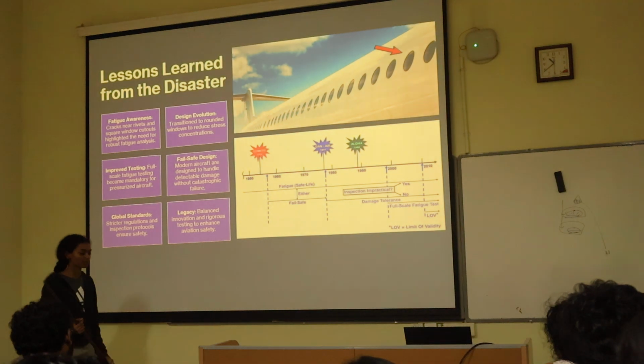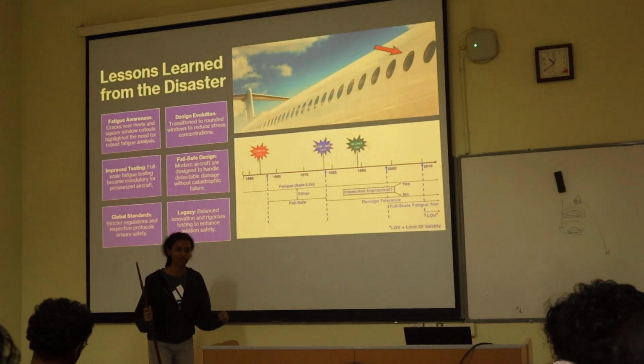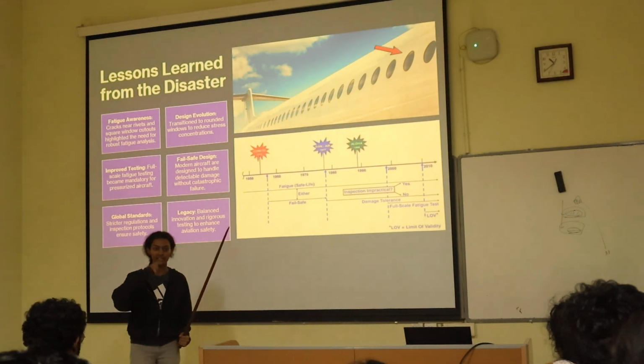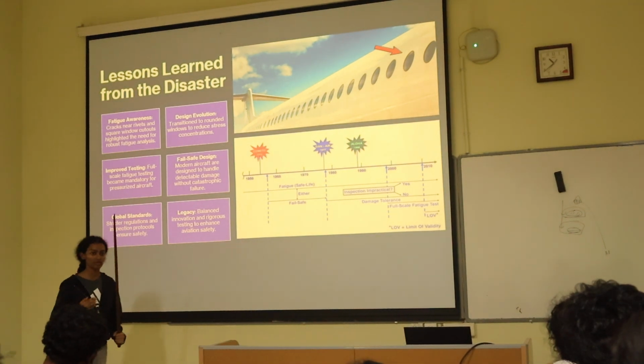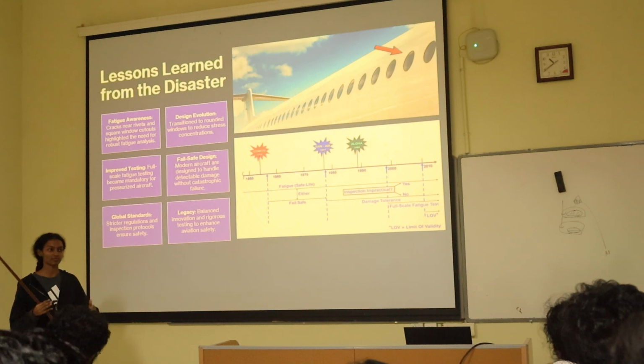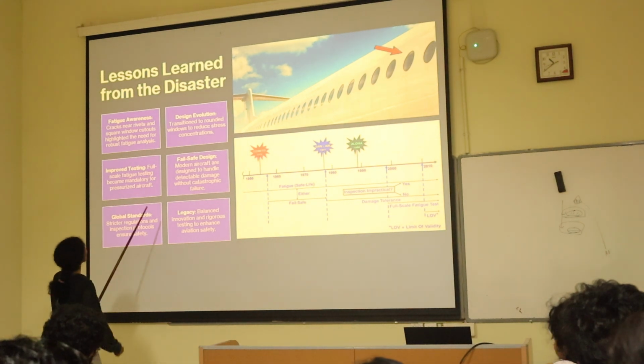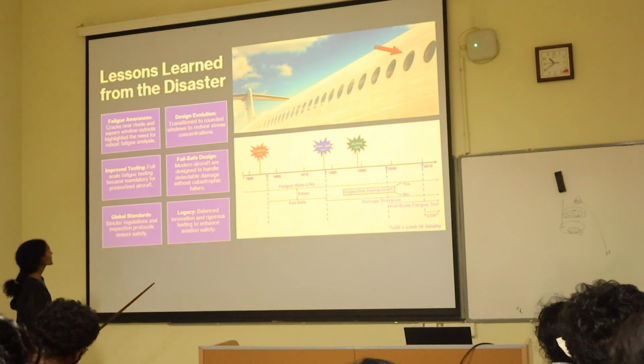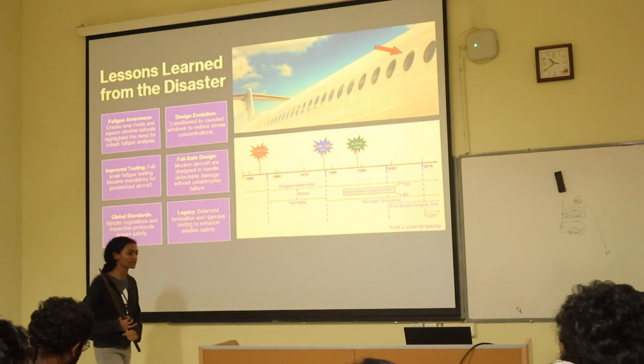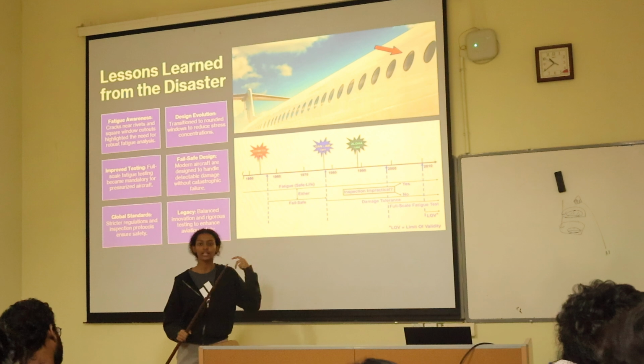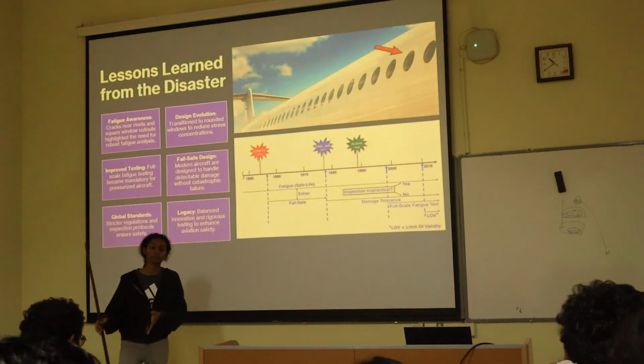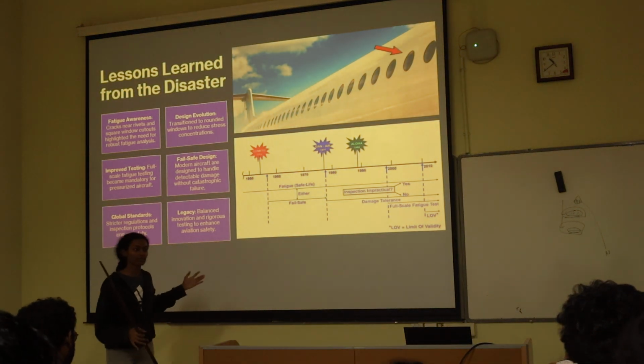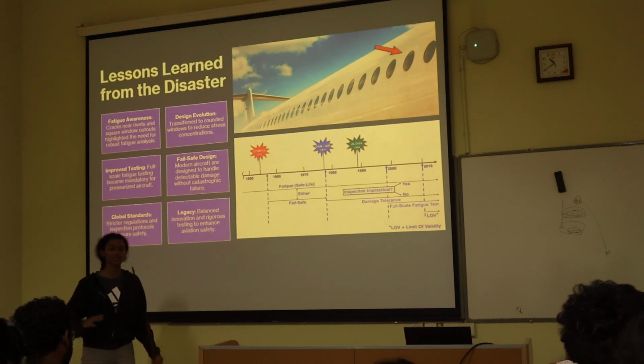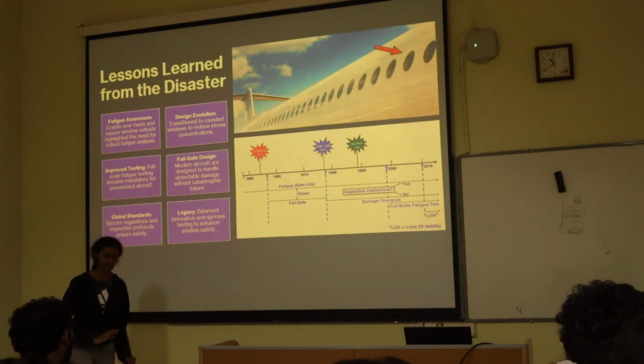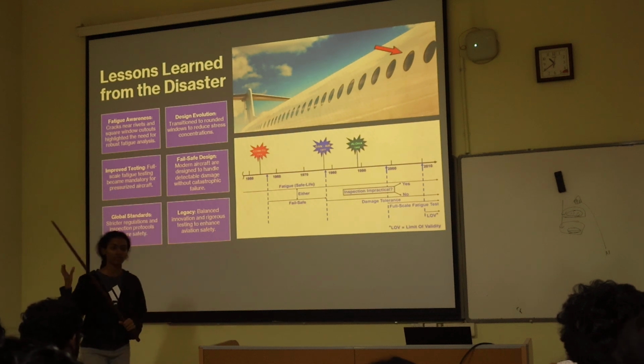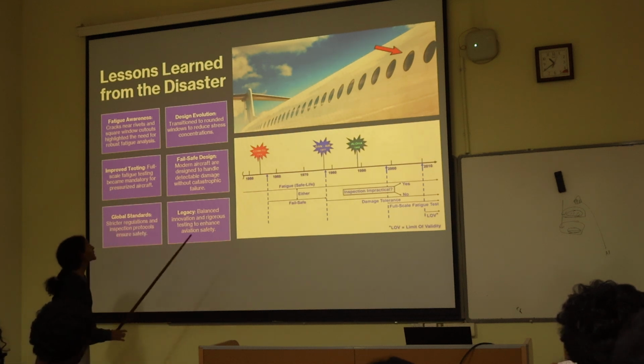Now, after realizing the problem with square windows, all planes have an oval shape and windows which do not have edges. And third, improved testing. The major mistakes they made while testing were to test at peak pressure and use the same sample to test fatigue. Now, in testing, they simulate what actually happens to an aircraft.